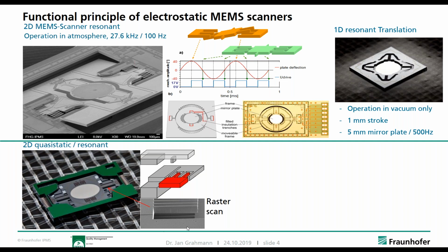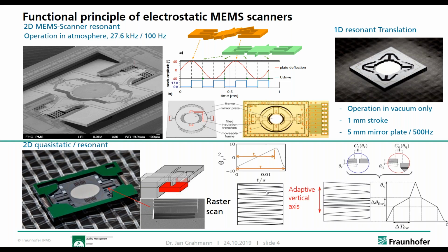And this is shown down here. And the concept to do this is animated on the slide as you see it now. So we have a top wafer with a stem that is bonded to the actual device wafer with the scanning mirror, and it deflects via certain actuation pads, creating an offset between the 2 comb electrodes. And this stays stable over time and allows us then to do a quasi-static actuation as seen here.